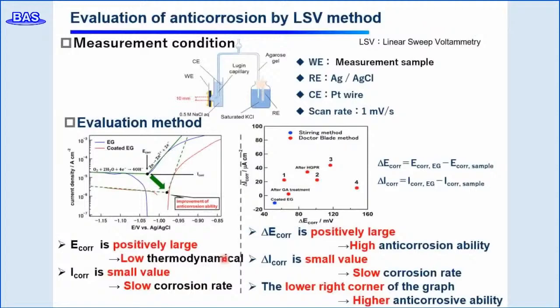Here is one example of a Tafel plot of our sample. We see oxygen reduction and zinc oxidation current at the positive potential regions. The intersection obtained by extrapolating the straight lines gives the corrosion potential and corrosion current density. From these results, we create this graph.